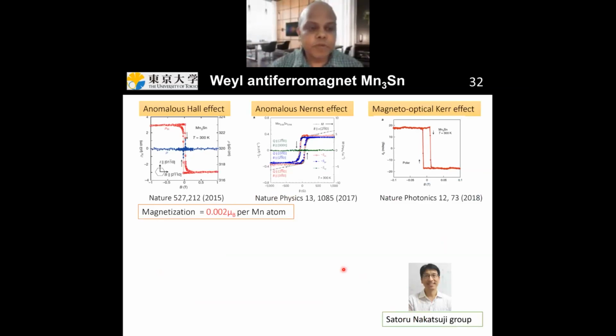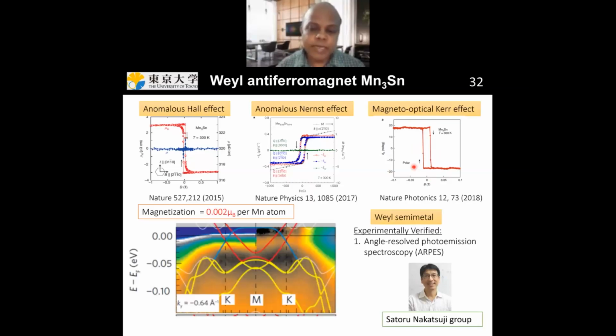It's a very, very tiny magnetic moment, but it shows a very large anomalous Hall effect, large anomalous Nernst effect, and large magneto-optical Kerr effect. So this was very puzzling to us. In order to understand this further, we also did angle-resolved photoemission spectroscopy experiments. And what we found was that the band structure contains these Weyl points, and these Weyl points have a large Berry curvature.